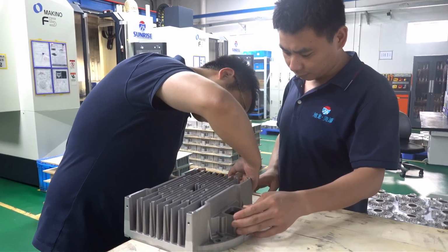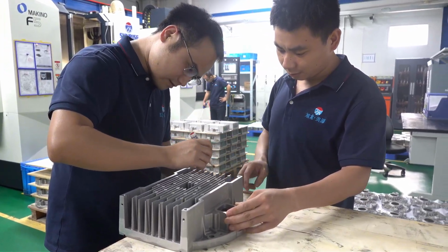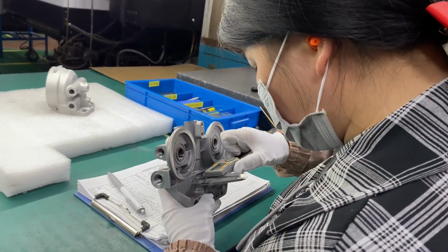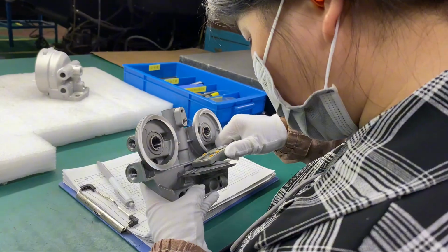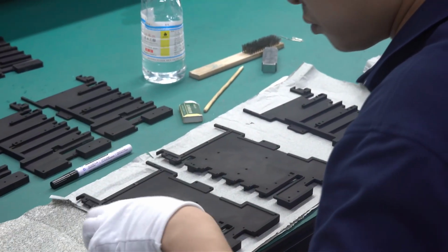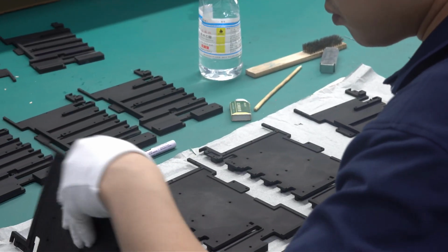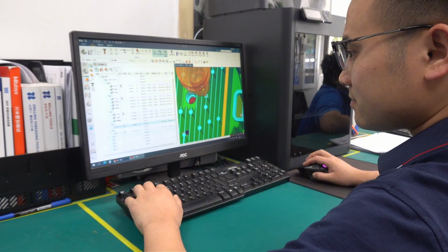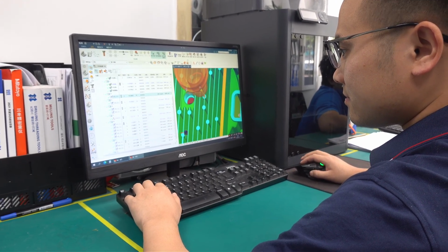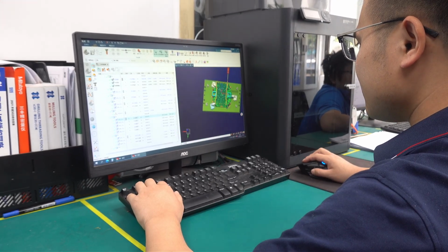Third, always consider draft angles and tolerances. Draft angles are slight tapers that allow the part to release easily from the mold. For aluminum, a typical recommendation is around 1-2 degrees. Tolerances aren't about being ultra-tight. Overly strict tolerances increase cost and risk failed parts. Set reasonable tolerances based on the material to reduce unnecessary machining. Follow this rule, and your design is functional, manufacturable, and efficient.